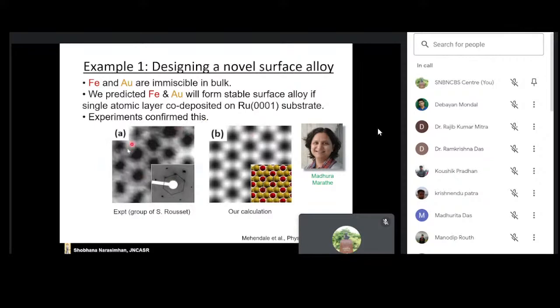After we made this prediction, experiments were done in the group of our collaborators, Sylvie Rousset in Paris. And this is an STM image of this system. So each of these black circles is an iron atom, and it is surrounded by 6 bright circles. Each bright circle is a gold atom. And this here is our simulated STM image obtained using density functional theory of the same system. So you can again see one iron atom, dark, surrounded by 6 gold atoms. Okay, so not only could we predict that this would be formed, and it was formed, and iron and gold are mixed at the atomic level, but we could also understand why this formed. So I had told you that in a DFT calculation, we can switch off effects. So what we were able to show is that the formation of this surface alloy is stabilized by magnetism.